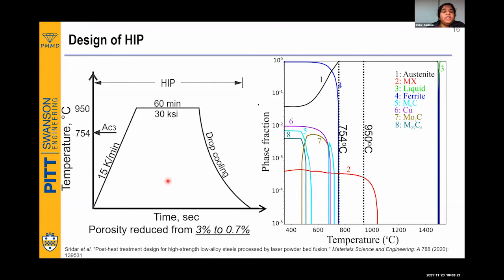So how are we going to design our HIP process now? We are going to have a heating rate of 15 Kelvin per minute. This was done in the company; they have a HIP machine which can only run a heating rate of 15 Kelvin per minute, so we didn't have the liberty to change that. We just go with it. A typical pressure of 30 KSI is found to be good enough for closing pores in AM parts. The time required is designed based on our previous studies, where we had already found the optimum homogenization time for this material without pressure. And the liberty we had was to design the cooling rate.